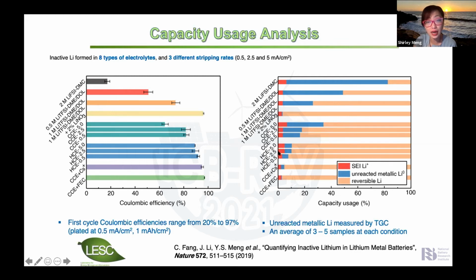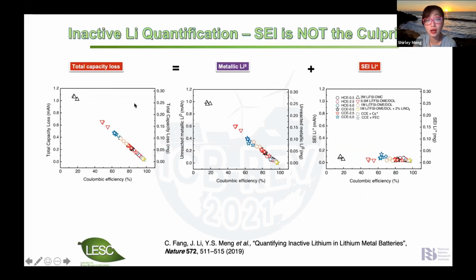And the different types of electrolytes have very similar SEI. The red part is the measured SEI component. So in the low Coulombic efficiency lithium metal cells, it's mostly due to the microstructure differences in lithium metal. If I plot the graph differently, you can see the capacity loss and the metallic lithium correlate very well. And the SEI is almost similar qualitatively in terms of its total amount.